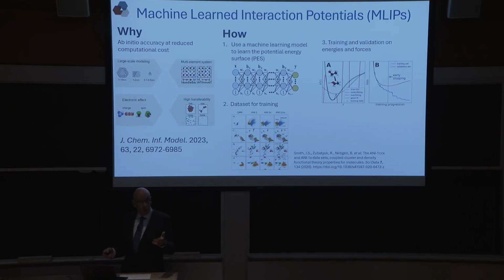And of course, there's DFT or quantum mechanics, which you can use to describe these processes, but it is very, very expensive. And one very good thing that's happened over the last several years has been the advent of these machine-learned interatomic potentials. So the basic idea here is very simple. Let's just do a few DFT calculations for a system of interest, calculate all the energies, all of the bond lengths, distances, torsional barriers. And then let's train a machine learning algorithm, a neural network, on the energies that I calculate. So in a sense, what you're doing is fitting all of these energies with a neural network that would allow you, hopefully, to describe all of the interactions between the system, many body interactions in this case, including bond formation, bond breaking, and chemical reactions of any sort.